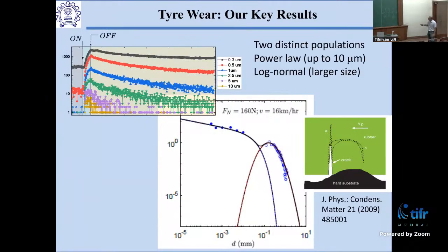And the data sort of looks like this, right? So you turn on the tire, you see a huge spike in the number of the particles that come off. And then when you turn off the tire, there's a small relaxation of the plastics. It's all enclosed in this big chamber to make sure it's all clean to begin with. And so the key result, and I just want to sort of give you this one key result, is that if you look at the particles that come off, and this is something that people hadn't seen earlier, there's two distinct kinds of the particles that come off.